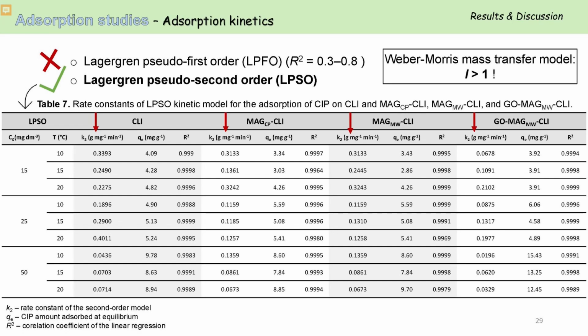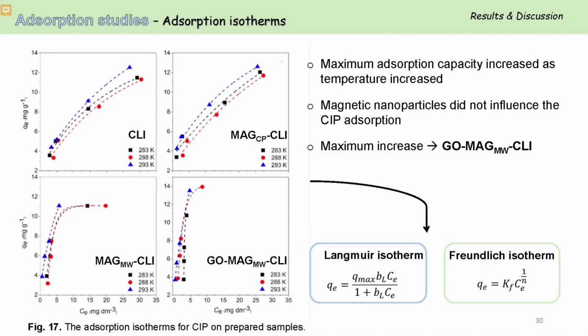And the analysis of the results by the Weber-Morris model shows that diffusion is not a rate-limiting step in the adsorption. The adsorption isotherms in general show that the maximum adsorption capacity increased with increasing temperature. Since the increase for the magnetic clinoptilolite composites is not so high, we can conclude that the magnetic nanoparticles did not influence the ciprofloxacin adsorption. On the other hand, coating with graphene oxide increased the clinoptilolite adsorption capacity for ciprofloxacin.